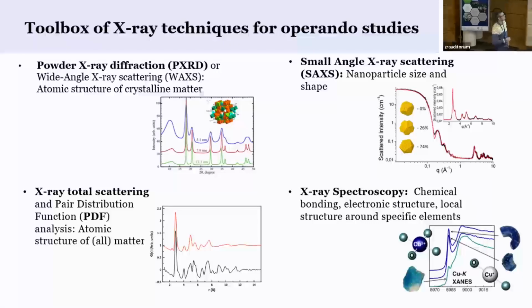So here are the different tools that you can apply. And important for us is really to look at the process operando or in situ. So typically we stop the electrochemistry while we do the measurement, so it's more in situ, but there's no real difference. We could also run the degradation test, although it takes quite a long time.